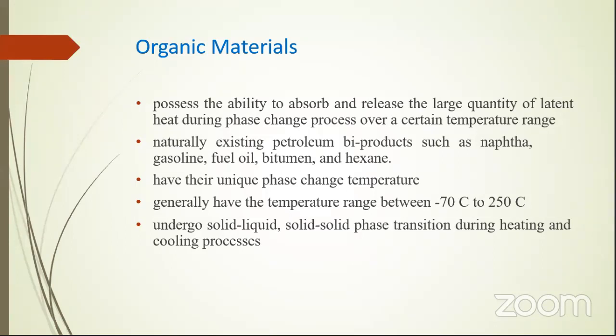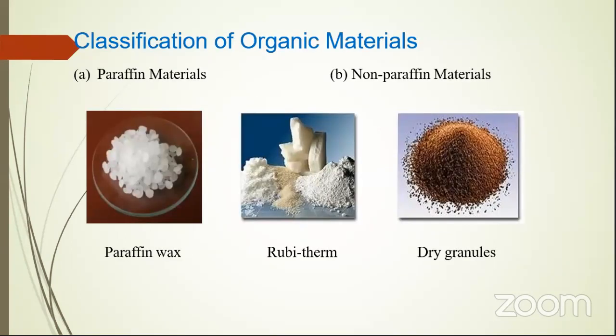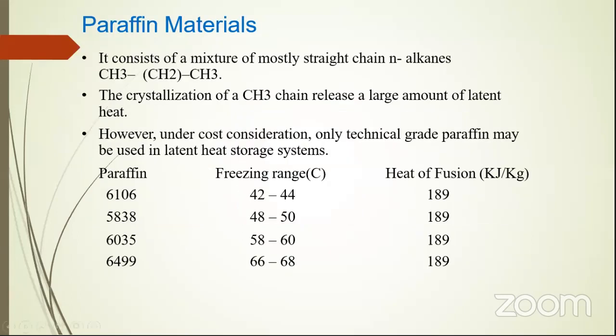And this is the classification of organic materials: paraffin materials and non-paraffin materials, and paraffin wax, Rubitherm, and dry granules. About paraffin materials, they consist of a mixture of mostly straight chain n-alkanes, and the crystallization of the methane chain releases a large amount of latent heat. However, under cost consideration, only technical grade paraffin may be used in latent heat storage systems. So only these are the standards we are using: 6106, 5838, 6035, 6499. These are the grades we are using.